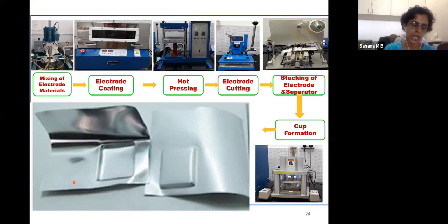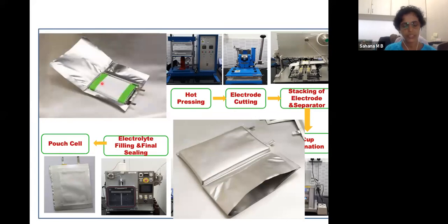This is an aluminum foil, but you know that aluminum foil is electronically conducting. So we have an insulating polymer coated over this aluminum foil, so that it physically separates the jelly roll from the covering. Then this is the final jelly roll with the leads. Then it's kept inside the cup and they are sealed here.